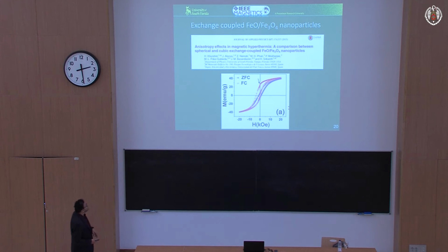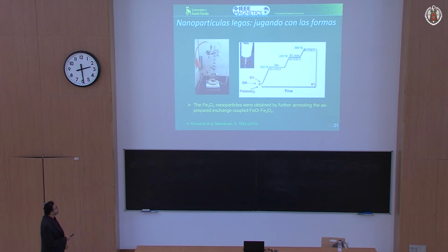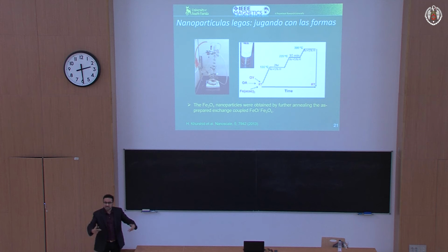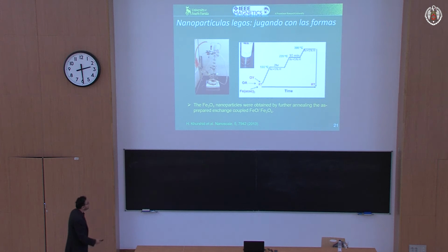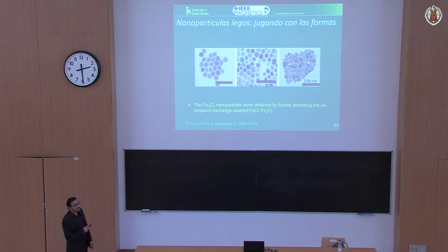So she went ahead and made these exchange coupled particles using similar techniques. And again, the main way we can change these shapes is by clever usage of surfactants, okay, to inhibit growth in certain directions, to allow growth in the others faster. So that's how we do this. So she made the same system. She made something nearly spherical, cubic, and also this exotic star-shaped octopods. Again, systematically varying the surface anisotropy, and we wanted to compare the SAR values. Okay, so the next slide I'm showing you is probably the most important slide of this presentation, because it's a direct comparison of the effect of anisotropy on the SARs.